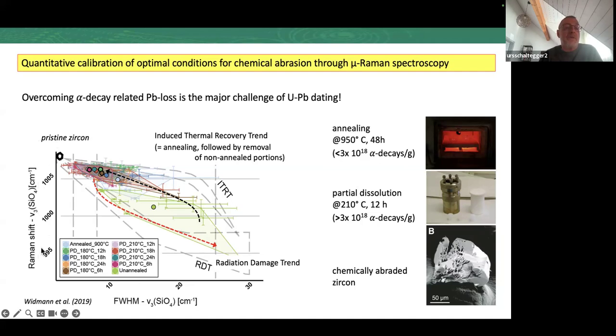This is a diagram showing the wave number of the Raman bands, the Raman shift, versus the full width at half maximum, so the shape of the peak. Pristine zircon would be at 1008 and have a very narrow peak. And then the radiation damage trend would go in this direction down here. What we do is we anneal them, so we go back in this process, but more importantly, we dissolve the more damaged grains away. So what Widmann et al. in 2019 proposed is a kind of area of confidence. When we are back here with our chemically abraded zircon, we can be rather sure that we do not have any more alpha decay related lead loss.